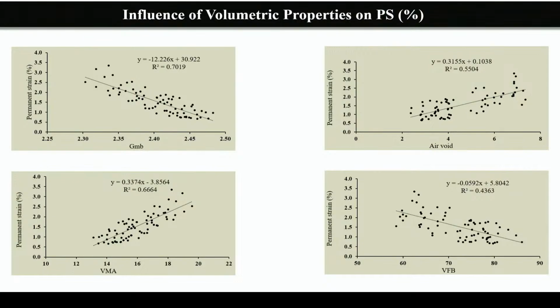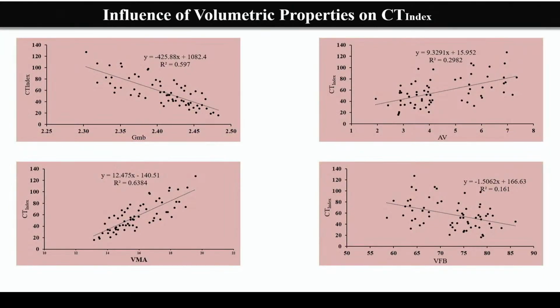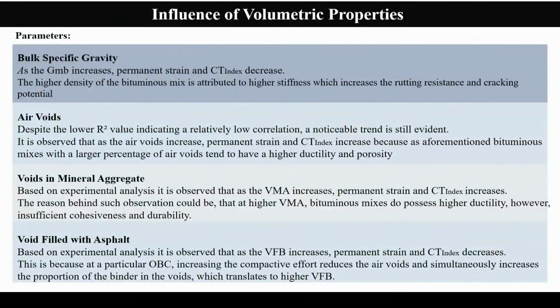Okay. So, as we have calculated all the performance, since we are following the volumetrics, we tried to find the correlation between the volumetric properties and the performance parameters. So the GMB and the VMA were found to have an excellent, better correlation rather than air void and VFB. So similarly, we tried to find it for the CT index.